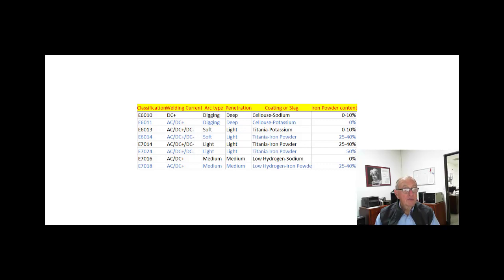So now, some of the description of the E6010 rod: it's known as typically deep penetration, digs through rust, oil, paint, dirt. A lot of pipe welders use it for the all position root weld passes on the pipe. So the 6011 can also be used for all position welding with an alternating current AC welding power source. Like 6010, the 6011 is a deep penetrating arc that cuts through corrosion or unclean materials. Very good for buzzbox welding, where you're working with not exactly clean material, stuff like that.